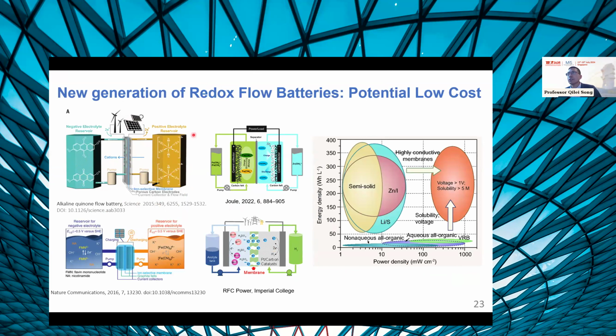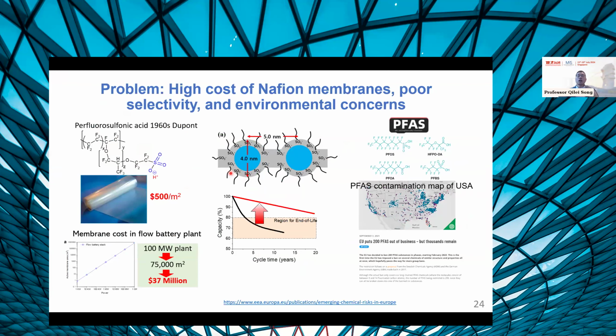In all of these new generation flow batteries, you can see that you're using two different materials at each side. That means if the molecules or materials cross over or diffuse through the membrane, then the capacity will decay. This is why we need to develop highly selective membranes to enable the long-term operation of these batteries. There are also problems with the membranes. Many of the flow batteries currently use the Nafion membranes developed in the 1960s. The Nafion membrane is not good. It's very expensive. If you scale up the flow battery plant, you have to use a lot of membranes.